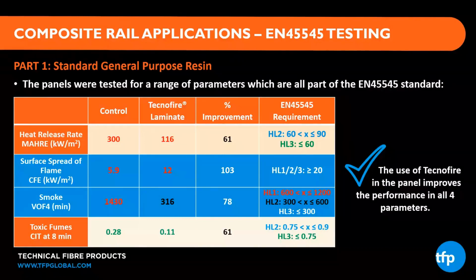It isn't an FST resin. It's going to act purely as a fuel source and burn and liberate a lot of heat. If we look at the impact of incorporating that 0.5 millimeter layer of Tecnofire, we've improved the MARE by 61%, the heat release rate, down to 116. So we've had a significant impact on the amount of heat that composite part releases in a